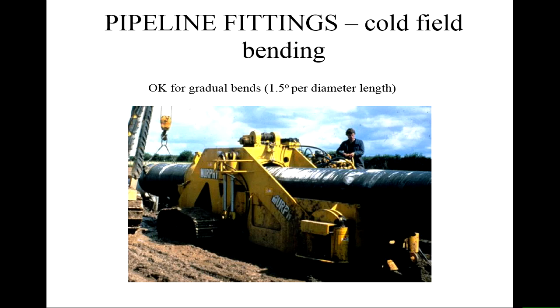If you bend it too much, the tube will collapse in the middle of the bend, and that will stop things going through. You will also buckle the outside of the pipe and cause quite a lot of damage to the metal, and that leads to weaknesses which you want to avoid. So we don't want to do anything where the bending is too significant, at least not cold.